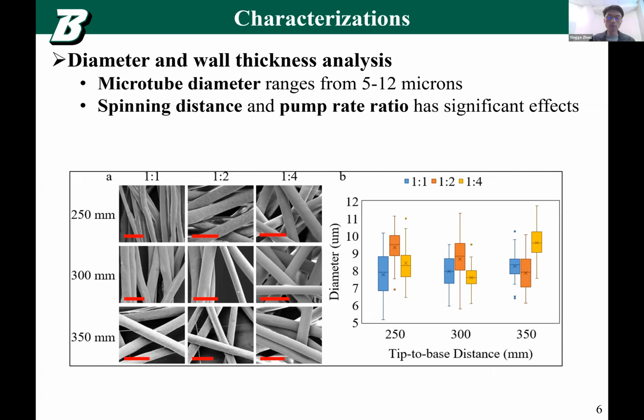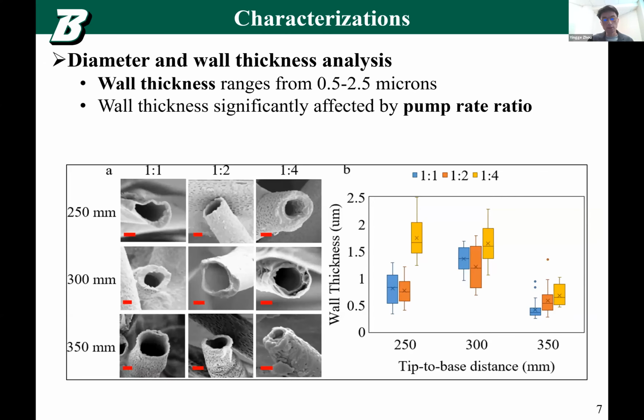Now we want to see if these two things have an effect on the microtube diameter, and it shows that both these two factors have significant effects, statistically important, P smaller than 0.05, on the microtube diameter. And the next one is wall thickness. You can see in the SEM image here, the wall thickness ranges from 0.5 to 2.5 microns.